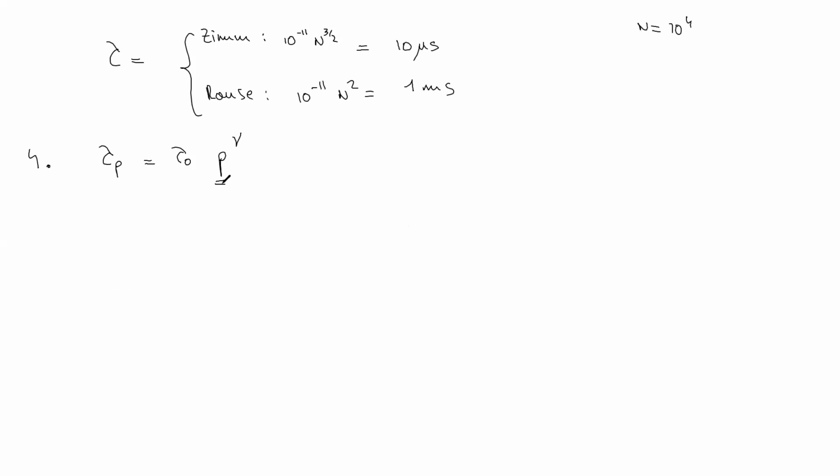So it's interesting now, a polymer chain. First of all, it's an object which is kind of spherical that moves in a fluid. So you have the degree of freedom associated to the center of mass. But at the same time, inside it, you have different time scales for relaxation depending on what type of feature you are considering. If you have a little knot or stress between two adjacent monomers, it will be really close to tau naught.